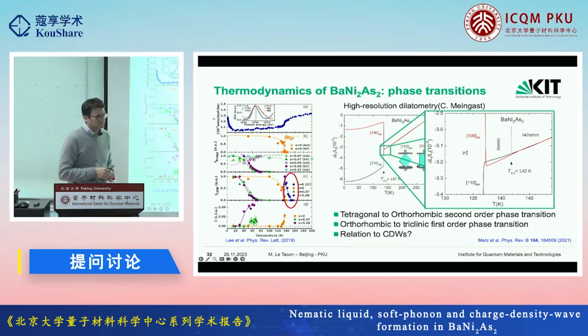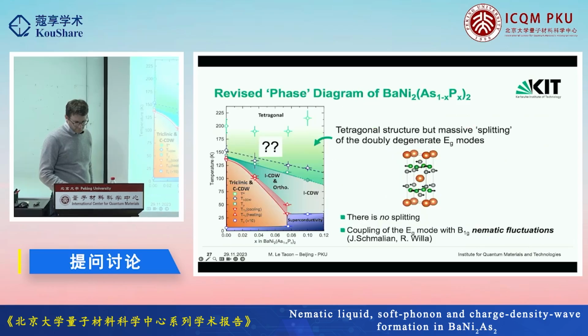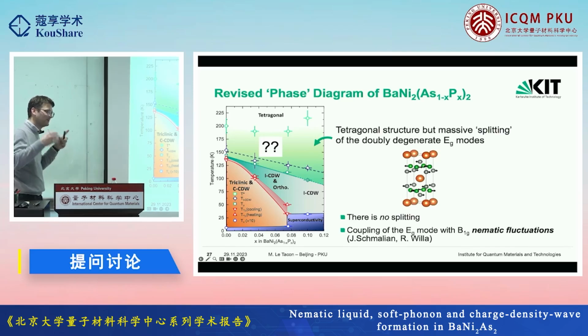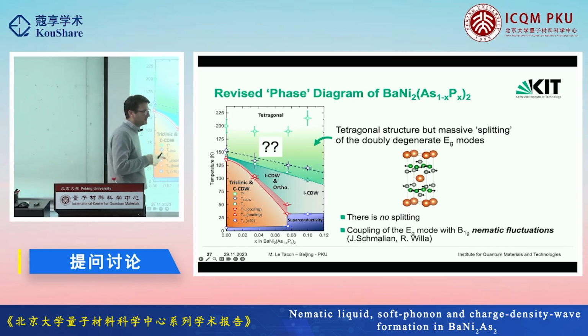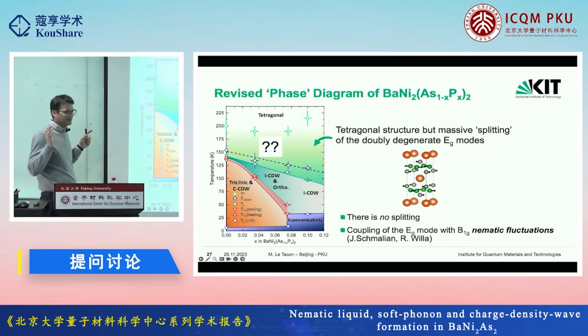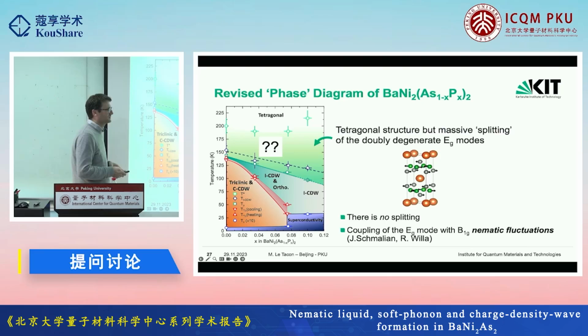I see. Thanks. Yes. So in the first part of your talk, you were saying that you have the electronic nematic order developing far above the structural phase transition, while the structure is still tetragonal. So besides this mode splitting, do you have any other evidence that you have this charge nematic order? That's the only experiment you have. Well, first of all, it's the only experiment, but I really want to emphasize again how not normal this experiment is. I mean, this splitting is just absolutely unacceptable. So it needs to come with some reason.